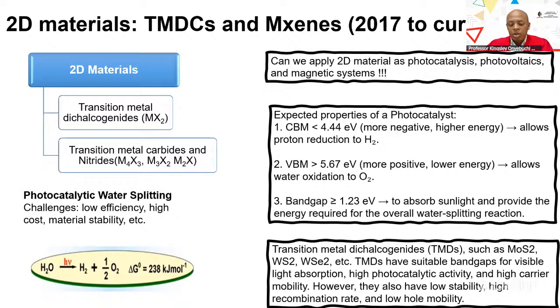But generally, MoS2, WS2, and WSe2, which are transition metal dichalcogenides, have band gaps within the light absorption range. They generally have high photocatalytic activity. But something that they suffer from is low stability, high recombination rate, and low hole mobility. When we talk about recombination, we're talking about the electrons and the holes combining. And we don't want them to combine, we want them to be separated. And this is a problem.